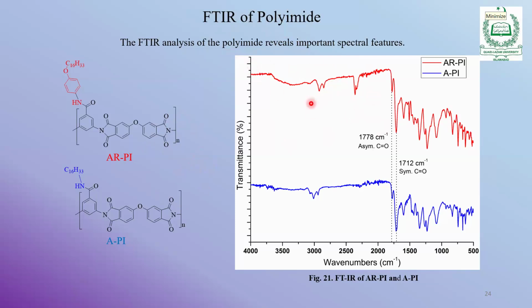The characteristic peaks for the polyimide formation are the two carbonyls, one arising from the asymmetric stretching vibration at 1778 per centimeter, and the other is the carbonyl symmetric stretching at 1700. So once we get these two peaks, we are sure that the imide linkage is formed. Also, you see no NH2s present here, which is also a very characteristic indication that the NH2s have been exhausted.